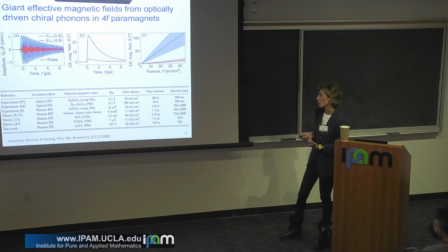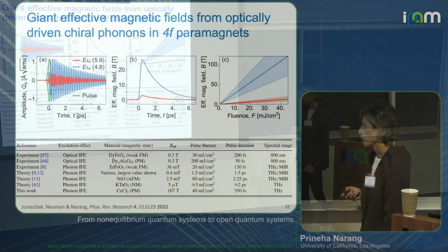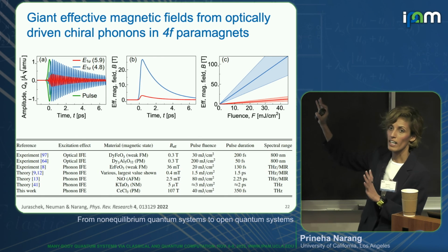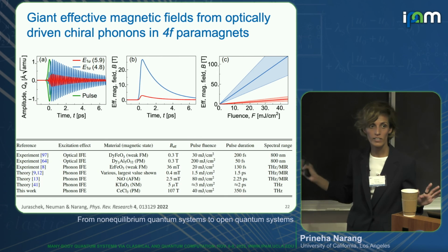And that is in contrast with other systems like nickel oxide, where we also calculated and eventually was measured the phonon inverse Faraday effect. That's on the order of a few millitesla. And some of the other systems have been more on the order of a fractional Tesla as opposed to tens of Tesla. So this is an experiment that is now underway, and folks are actively working to realize this in cerium trichloride. And I want to say this is something that is general beyond cerium trichloride.